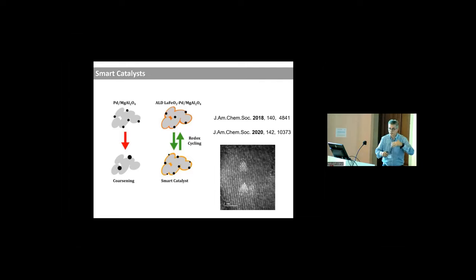smart catalyst. Because under redox conditions, oxidizing and reducing conditions, you can have exsolution of the particles from the bulk to the surface and vice versa. And I would like to emphasize how quickly under real industrial conditions you flip from oxidizing to reducing conditions. So this is something more and more interesting for companies.